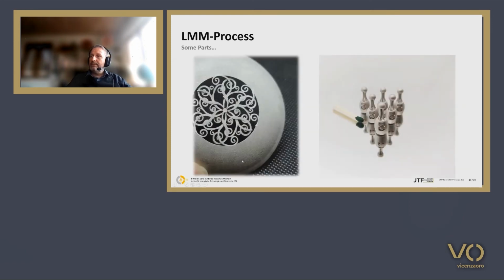Here, this part looks very interesting, very nice if you have a first look at it, but the thing is, it's a reject part, and I chose it for two reasons. First of all, you see that very delicate structures can be printed. And secondly, you see that this part has not been cleaned properly. Here with the ultrasonic bath, we didn't get out all the not exposed printing material.